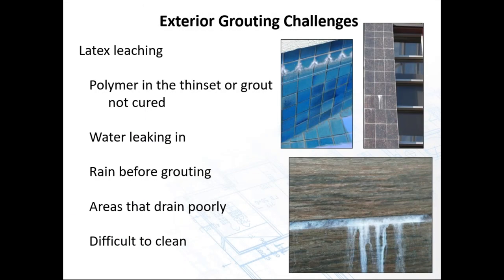The other problem that we look at on tile installations, a lot of times it's confused as efflorescence when it's latex leaching. Latex leaching is when moisture has gotten back into the mortar beds and is pulling the latex to the surface. Moisture got into it, the substrate wasn't allowed to properly cure before getting wet. We've seen installations where the tile was put up and a heavy rain came before it was grouted.